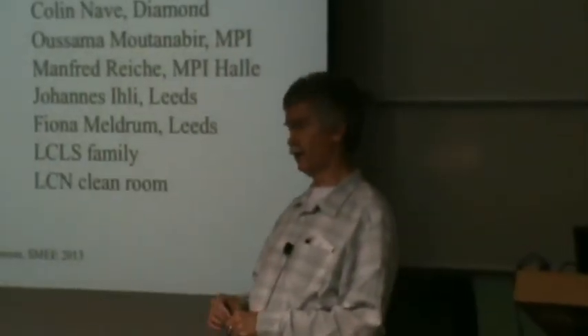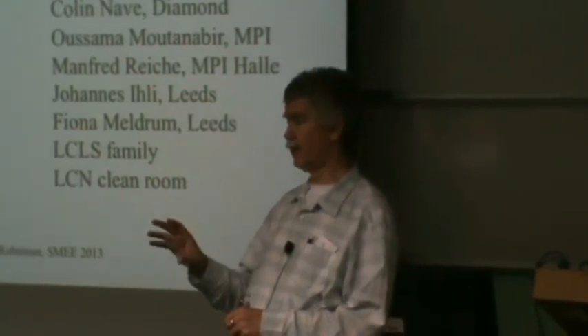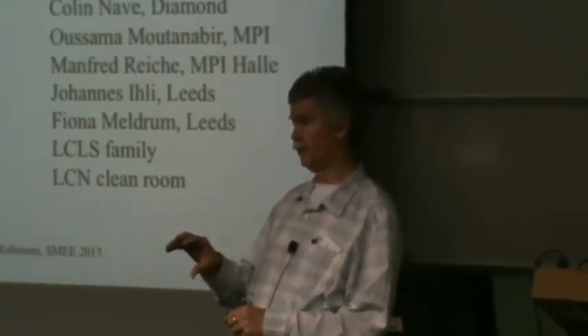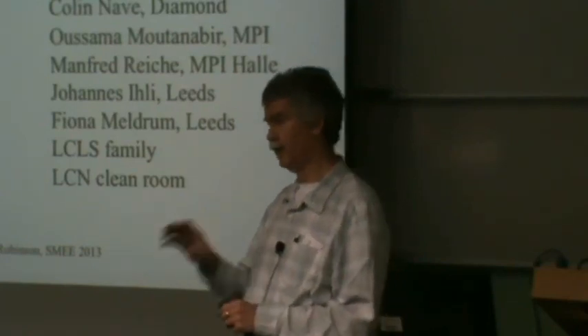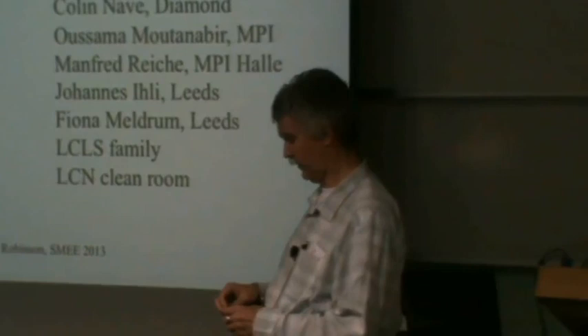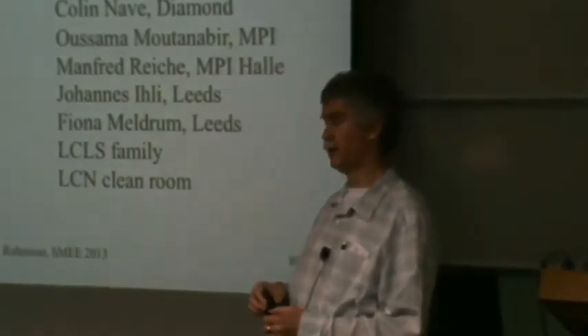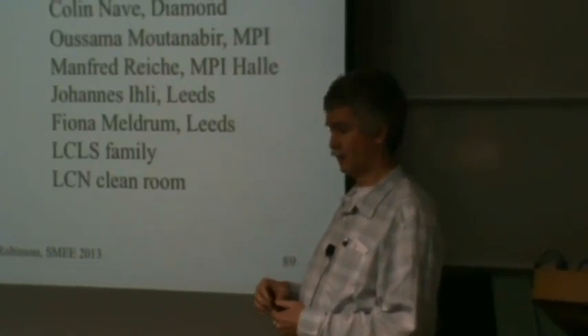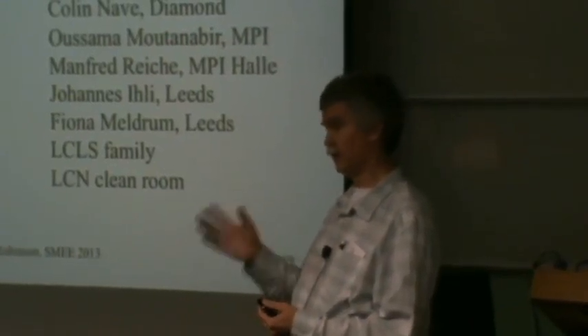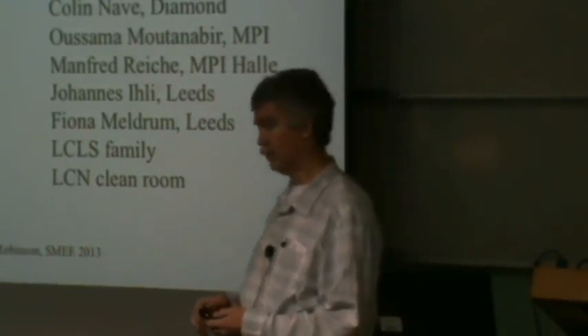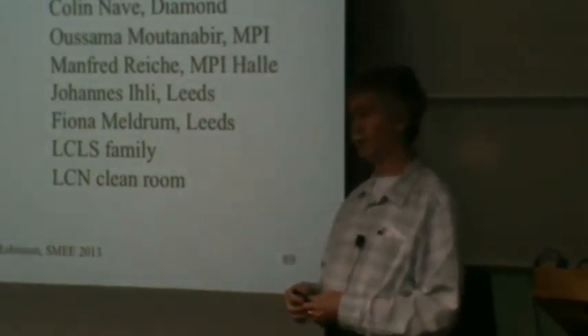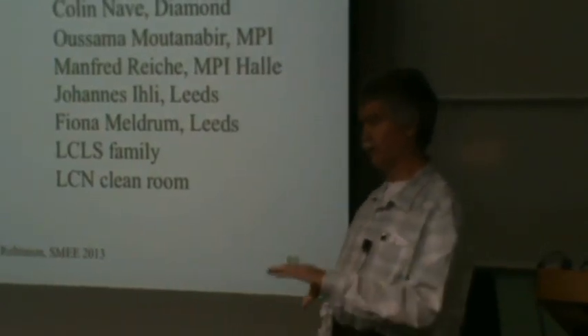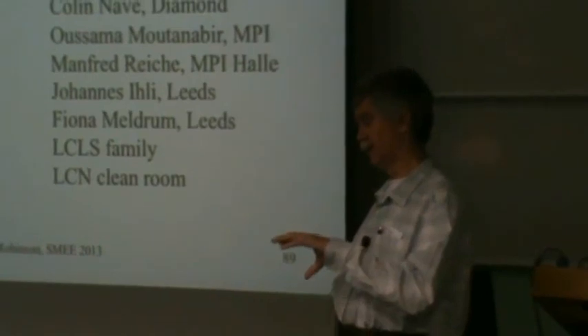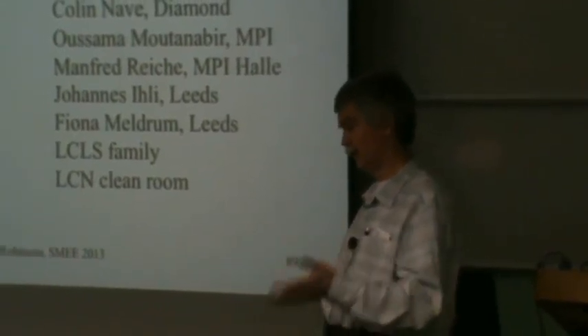Well, you fry some to calibrate the lasers, right? So both the optical laser and the X-ray laser were turned down from their maximum flux. So in the case of the X-ray laser, about a factor of 10, because it was already focused, and the focused beam, nothing survives. So we had to attenuate that by about a factor of 10. And also the optical laser, we had to attenuate that or it would just burn holes in the sample as well. So we're working below the threshold for both lasers, which is experimentally determined. So you sacrifice a lot of crystals learning what those levels are. But once you get below the level that the sample survives, it survives for many hours.